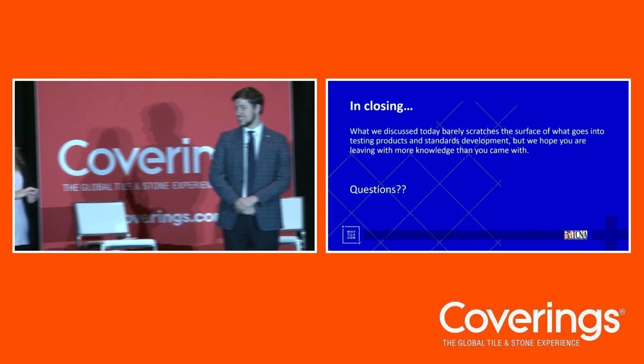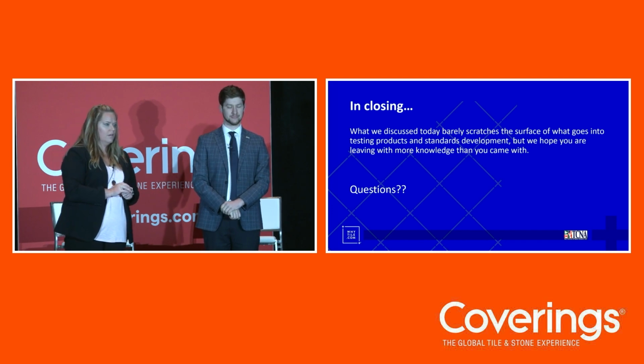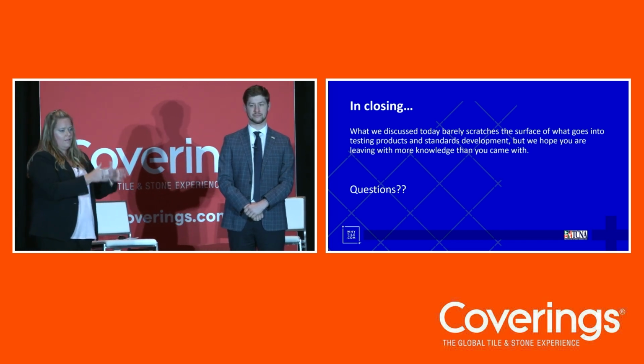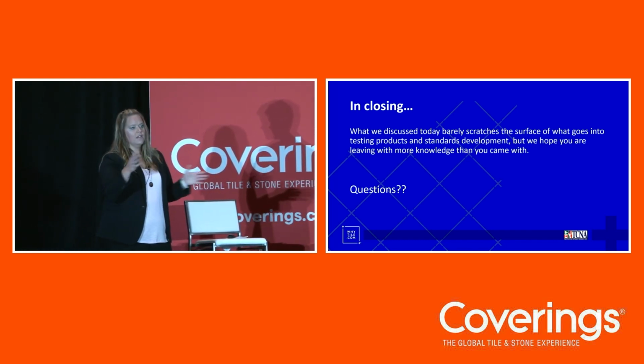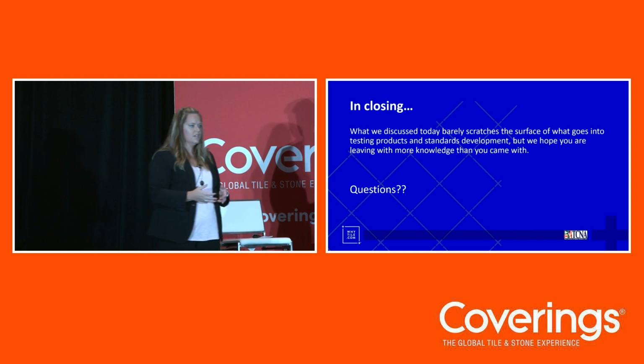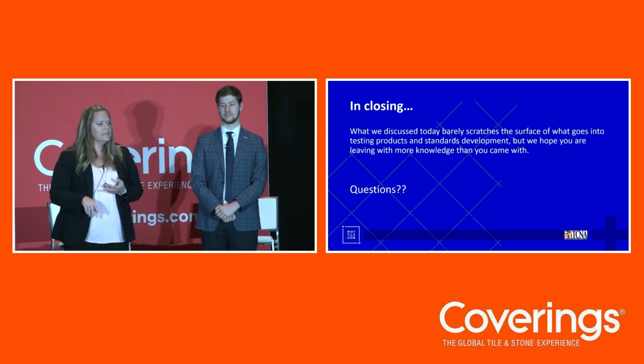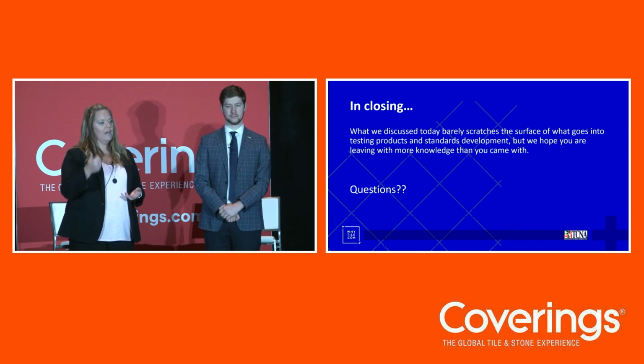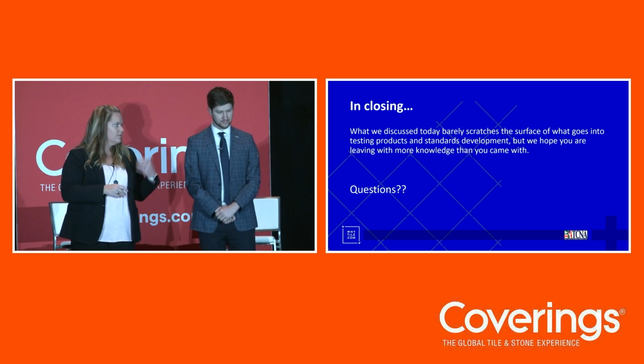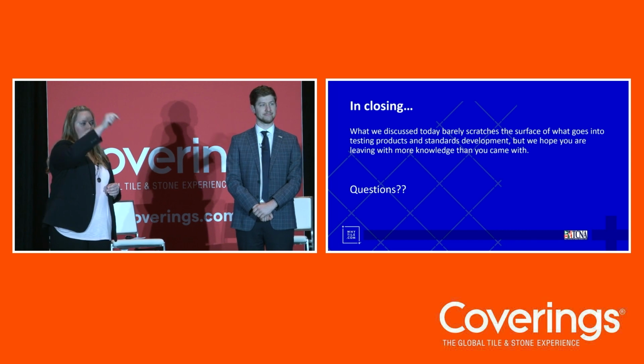So, I think one of the key things about A326.3 is it has a section on field testing. One of the important things we should do is continually check a flooring material, because that can happen. You have a flooring that starts out and meets the requirement in A326.3, but over time, especially in heavy traffic areas, it may drop. It may decrease in DCOF, but that's why you need to continuously check it and have proper maintenance. And there are products out there that can help bring that value back up. That's why it's so important to maintain and continually check, and one of the reasons that field testing procedure was included in A326.3.